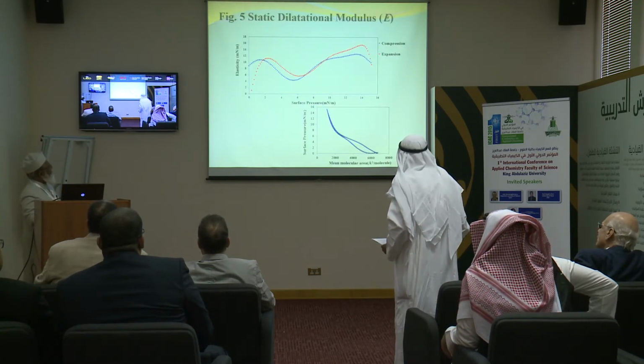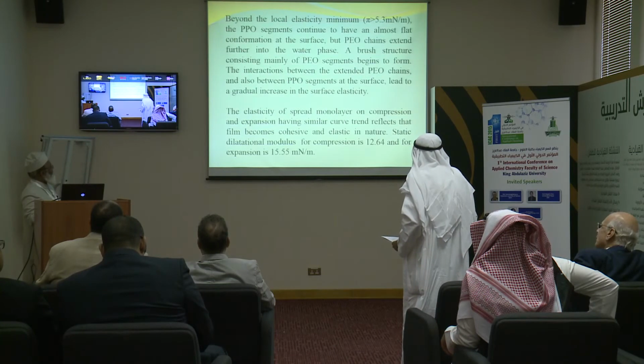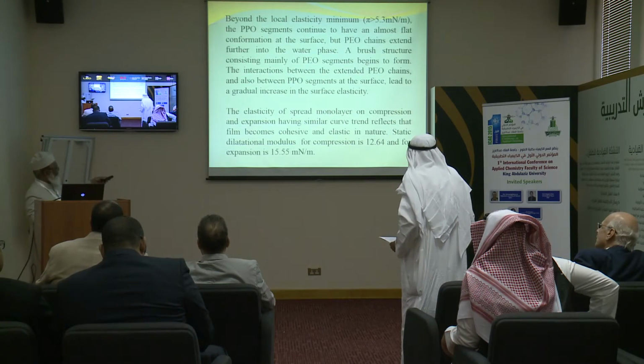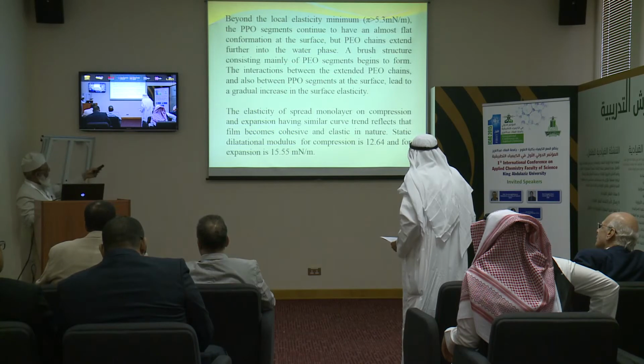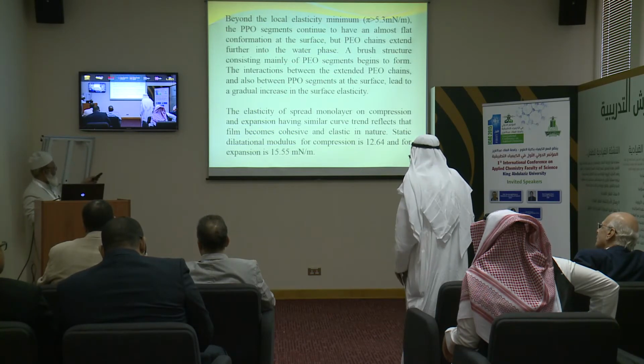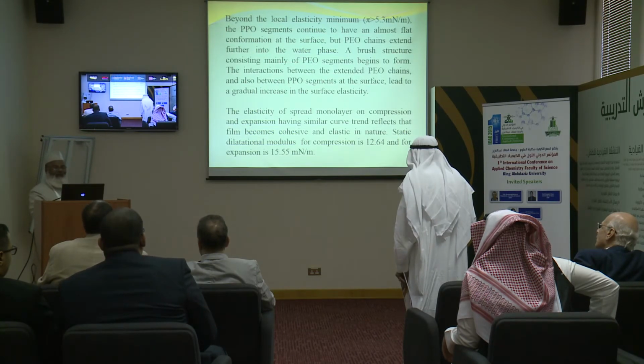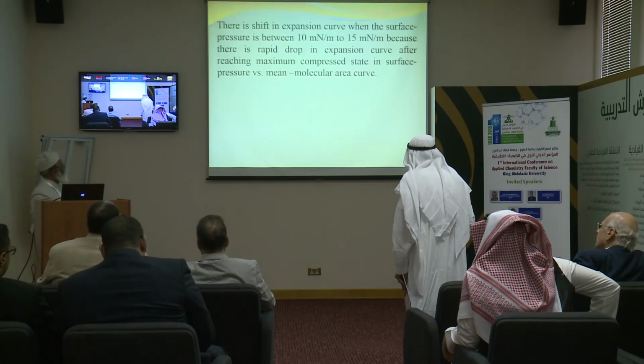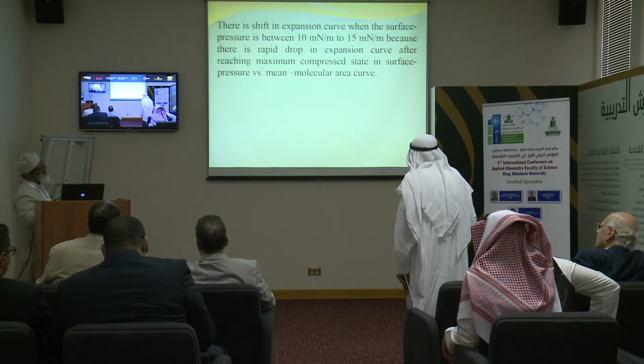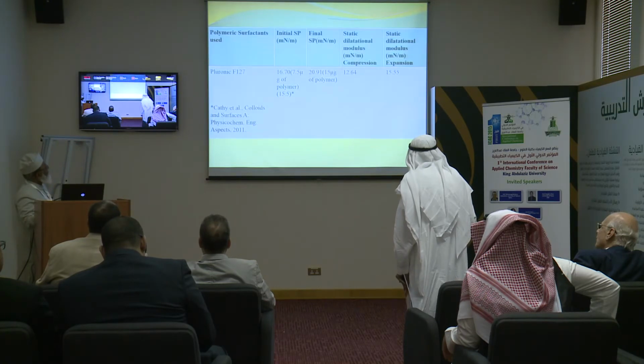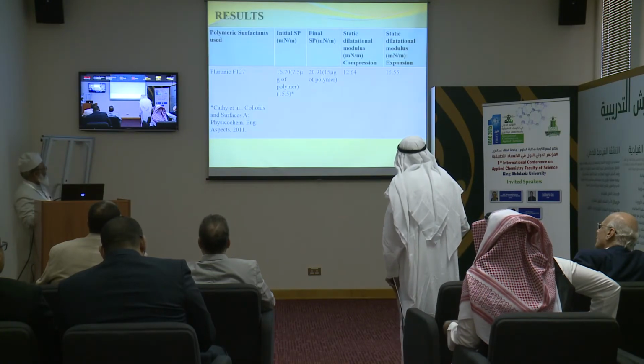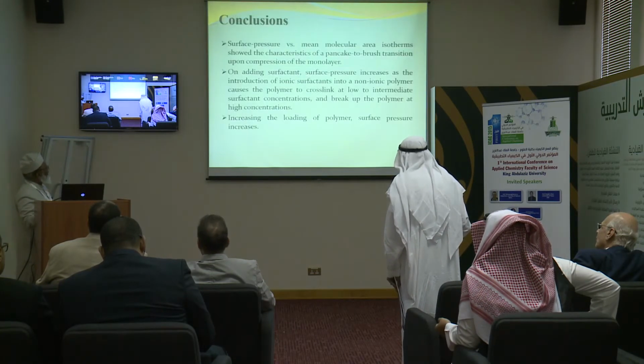This is regarding the dilatational modulus, and the elasticity of the monolayer on compression and expansion having almost similar curves, which reflects that the film becomes cohesive and elastic in nature, and the value that has been reported is also quite comparable to that in the literature. These are the results which have been obtained for the film.